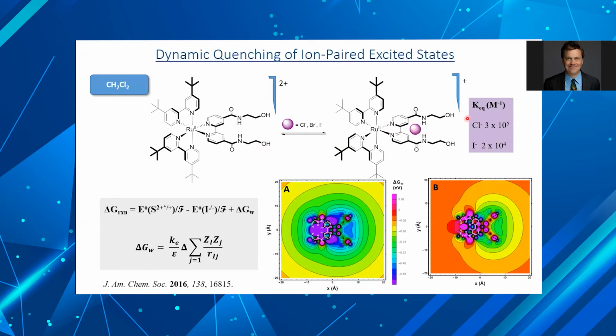And what we found was that when you put a chloride or an iodide in this pocket, it stabilizes it. A lot of this equilibrium constant is due to stabilization of the ion, and it becomes very hard to oxidize that. So it's an important lesson. If we can take molecules or interfaces and put them in seawater and selectively bring the chloride in and bind it there, suddenly that chloride becomes a lot harder to oxidize than all the other chloride ions that are diffusing around in solution. So how do we oxidize just that one? And that's a challenge for us.